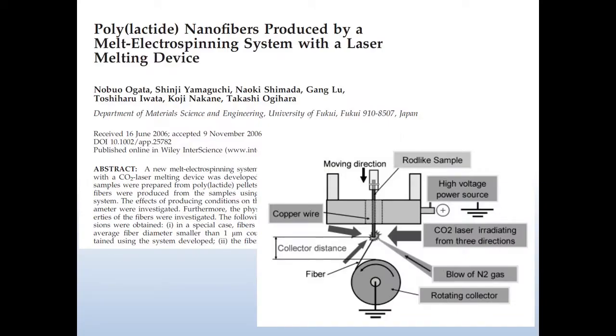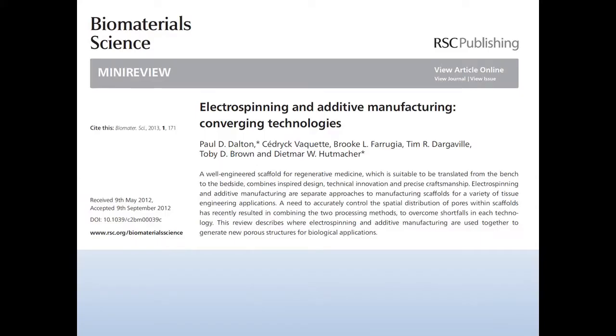But I think, importantly, one aspect that has been done actually since 2006 is laser melt electrospinning, where you have a solid polymer stick and you feed it into a laser. And the faster you feed it into the laser, the faster the flow rate. And you can get nice structures from that. And the important thing here is that this is cold, this is not thermally degrading, and then it goes hot and then it goes cold again. So that thermal effect. And this is important when you want to get beyond PCL.